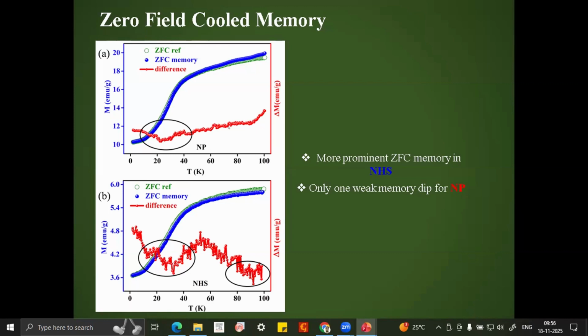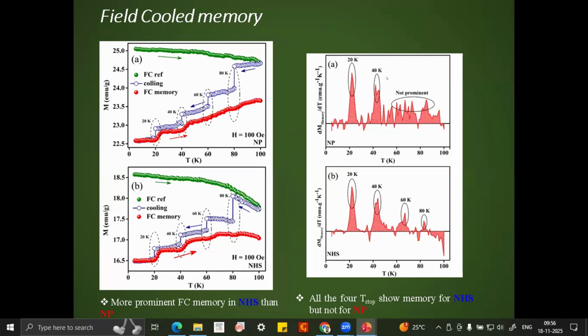There are a lot of theory papers also. I have measured it for the nanoparticle: if any superparamagnetic nature is there, I have shown that a very weak zero field cool memory is there. On the other hand, a very strong zero field cool memory is there for the nano hollow sphere. So I have been consistent in every talk. I believe there is a dominance of superparamagnetic nature in the nanoparticle, because we observe it experimentally. We cannot say there is no superparamagnetic nature in the nano hollow sphere also, but we can say that superparamagnetic nature is dominant in the nanoparticle, while the spin cluster glass nature is dominant in the nano hollow sphere. Also, the magnitude of the field cool memory is a significant indicator of whether your system is superparamagnet or spin glass. I hope that answers your question. Okay, thank you.